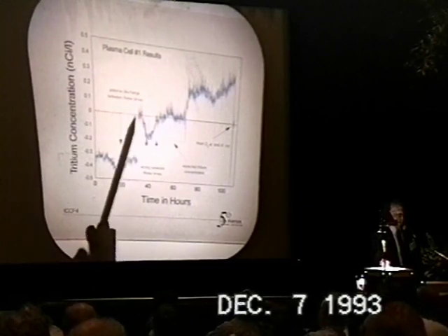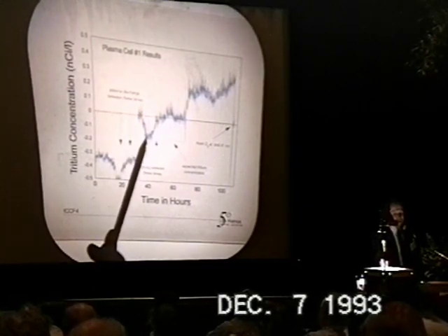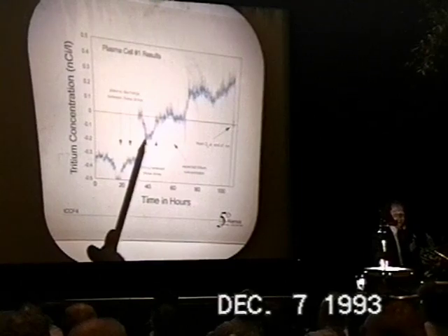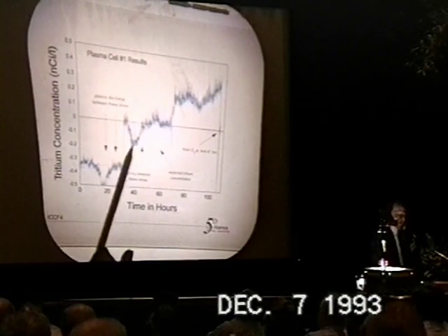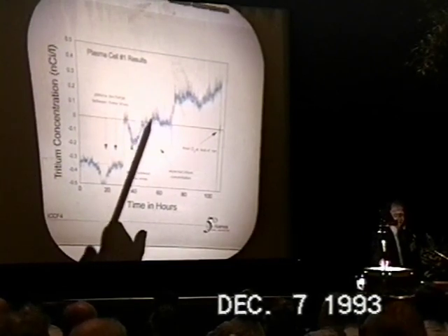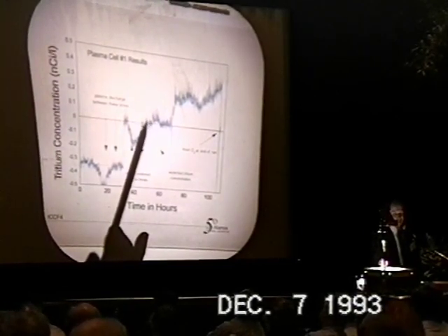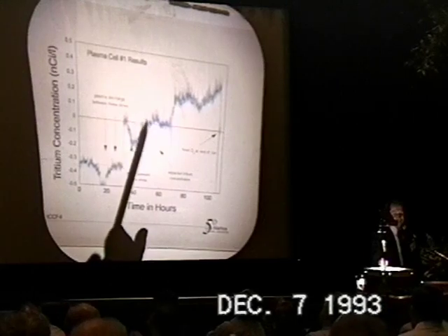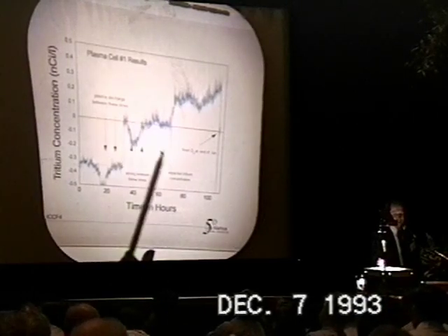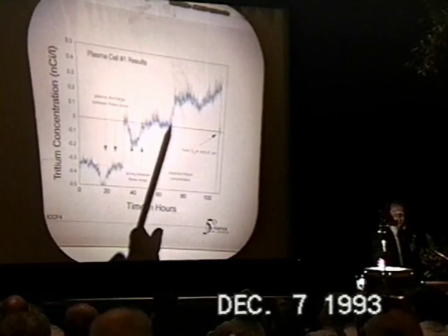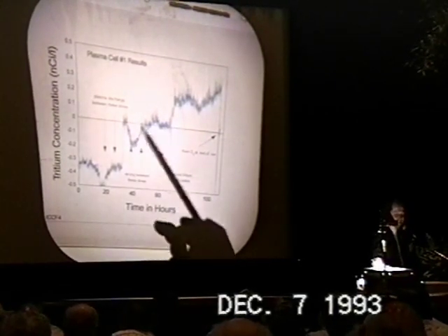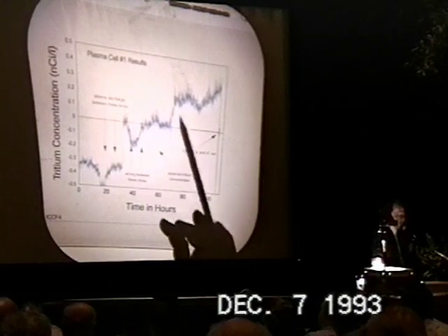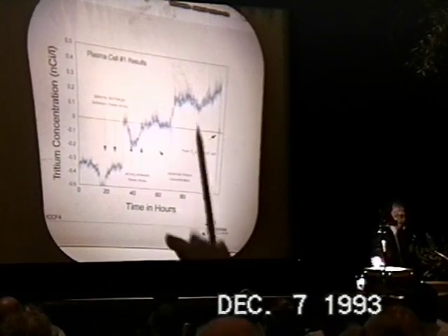When we increased the pressure, we had to turn up the voltage, and then decreased, we increased to 700 and back to 400 torr, and increased the voltage trying to get the plasma starting again. What we actually got was arcing. And during this period, we had significant arcing. It's during this period that we believe there was an increase in the amount of tritium. At this point, we raised the pressure back up to 700 torr, and this same delta that's produced here shows up. I don't believe there was anything happening during the rest of that.